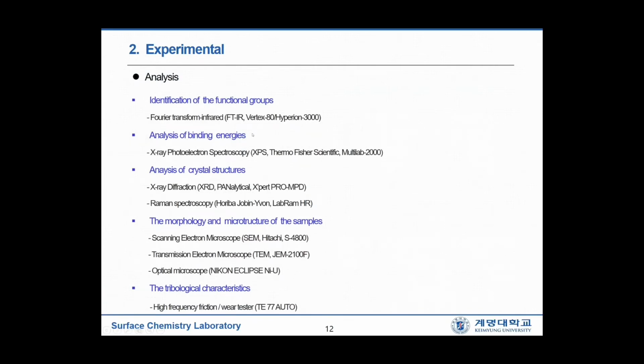These are the analysis techniques that we have used in characterizing samples. FTIR is used to identify the functional groups of FGO. XPS is used to analyze the binding energies of elements of samples. X-ray diffraction and Raman spectroscopy are used to analyze the crystal structures of the samples. SEM and TEM are used to analyze the morphology and microstructures of the samples. The tribological characteristics are investigated by the high-frequency friction wear tester.